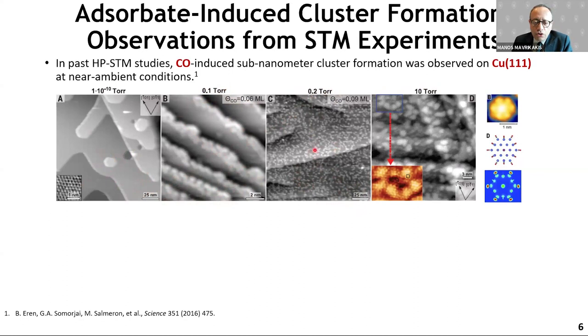you now see lots of dots on the terraces and close to the step edges and all around. These are clusters of copper atoms, it turns out. And then if you go to even higher pressure and you zoom in back, you see much more corrugation compared to the previous cases. And with the STM, they managed to figure out that each one of these clusters of copper atoms is more or less something that is schematically shown here.